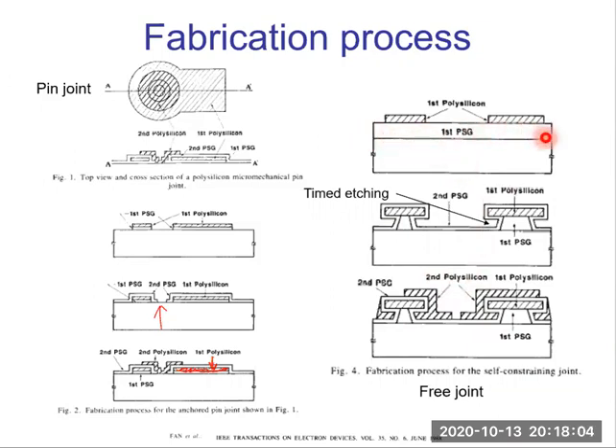Deposit first PSG layer, then deposit and pattern first polysilicon layer. That's the first step. Then etch first PSG layer. The first PSG layer is etched using the first polysilicon as a mask, actually. Then deposit second PSG layer. Note that for free joint, we do not pattern the second PSG layer. You can compare this step with this step for pin joint. You can clearly see the difference.